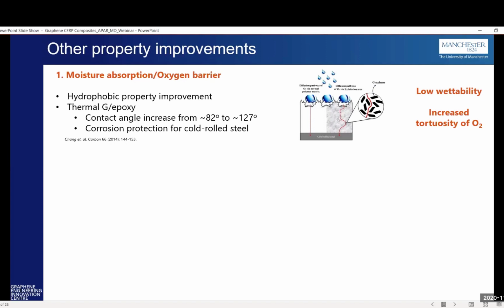One type of material, graphene oxide or reduced graphene oxide, can be used as it has hydrophobic properties which you could tap into to produce a hydrophobic material. In one of the studies, they showed an improvement in the contact angle from 82 to 127 degrees, and they were using this particular material as a corrosion protection for a cold rolled steel application.